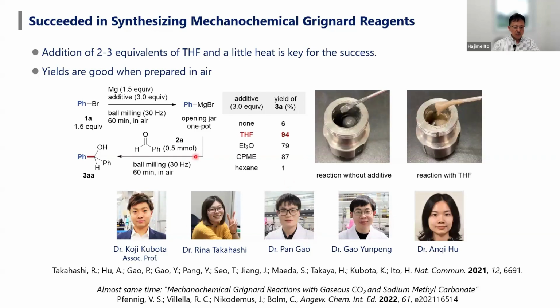But we found that adding 2 or 3 equivalents of THF can improve this reactivity very much. Sometimes we also heated up the reaction jars. So we found that Grignard reagents can be synthesized very efficiently under ball milling reaction conditions.